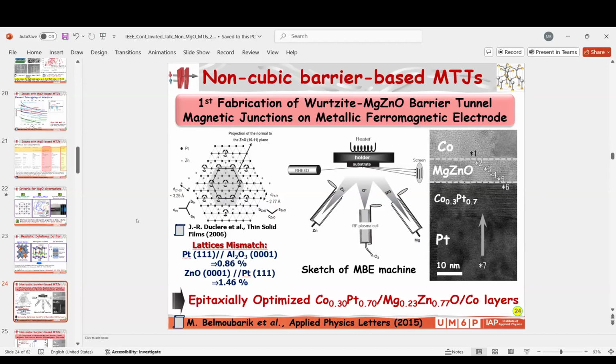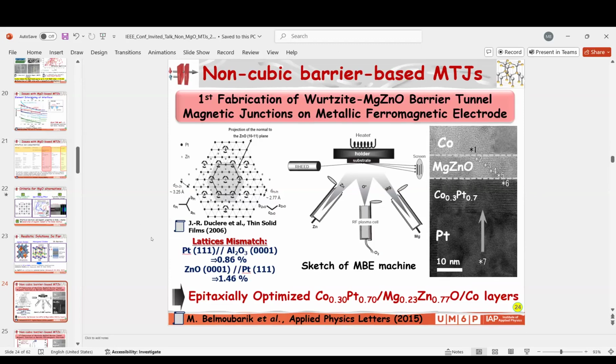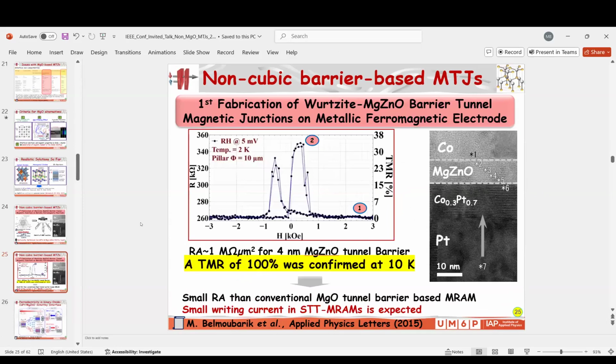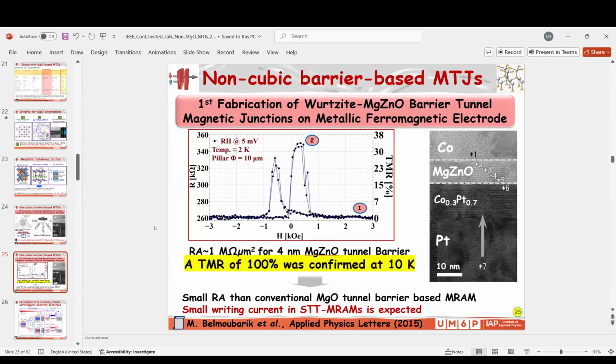Allow me to drink some water. So we could realize a TMR of up to 100. This is very nice. Sorry if I couldn't bring the picture, but this result is under preparation, and we could at least get a spin polarization beyond the bulk one, for example, for cobalt platinum and cobalt. Please visit our paper here to get more insights about these things.